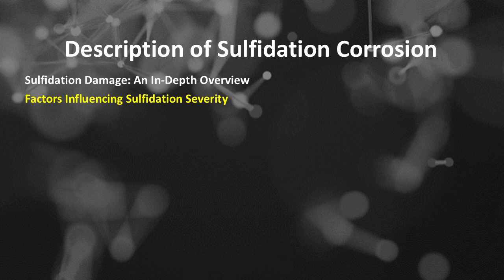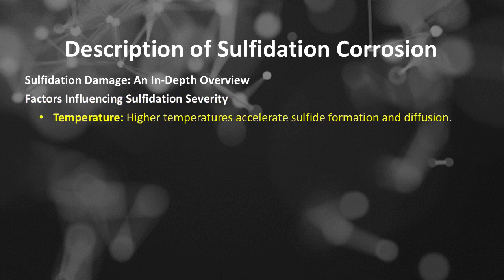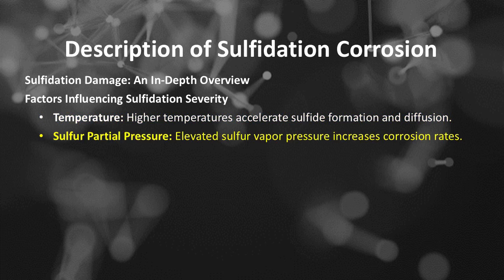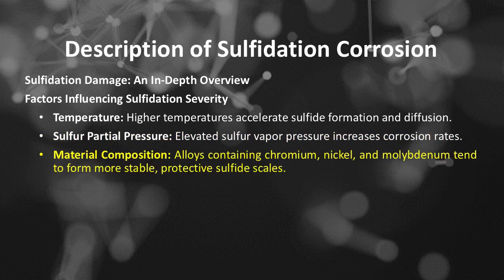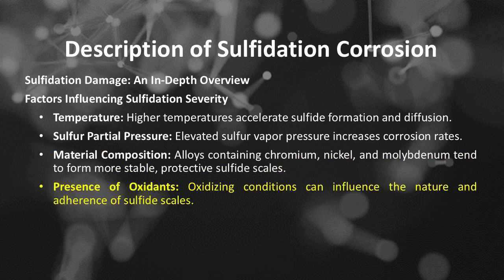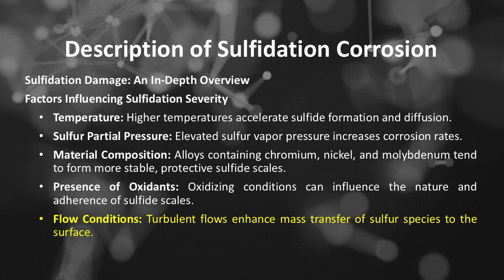Factors influencing sulfidation severity. Temperature: higher temperatures accelerate sulfide formation and diffusion. Sulfur partial pressure: elevated sulfur vapor pressure increases corrosion rates. Material composition: alloys containing chromium, nickel, and molybdenum tend to form more stable, protective sulfide scales. Presence of oxidants: oxidizing conditions can influence the nature and adherence of sulfide scales. Flow conditions: turbulent flows enhance mass transfer of sulfur species to the surface.